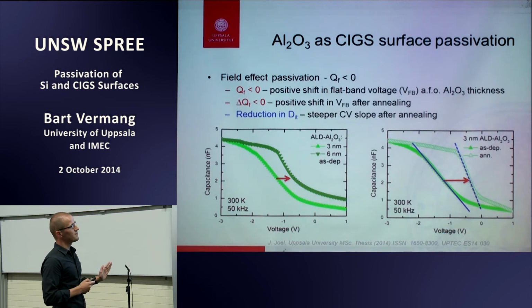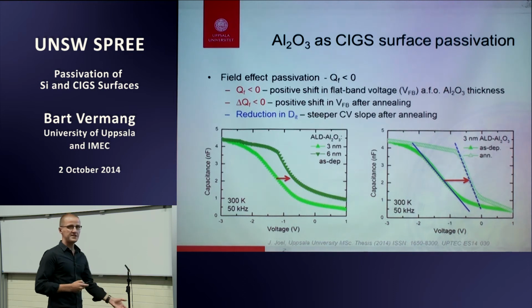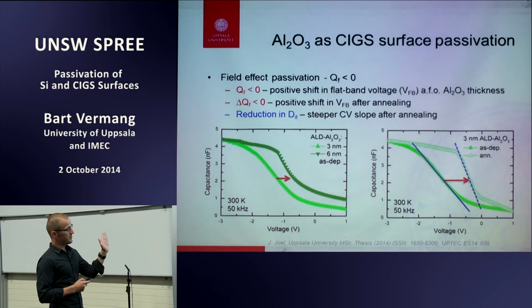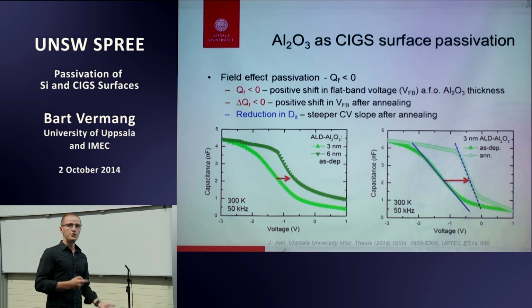You see a shift in flat band voltage from the left to the right, or to more positive voltage, which indicates again a negative charge density within the aluminum oxide. And also the slope becomes more steep, which indicates that the interface trap density is even improved after annealing, which might indeed be the case.